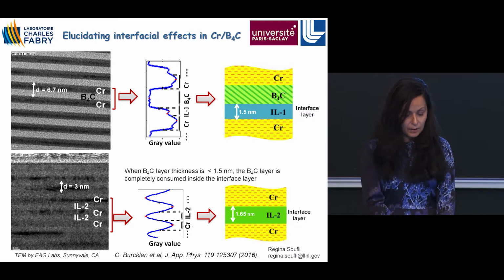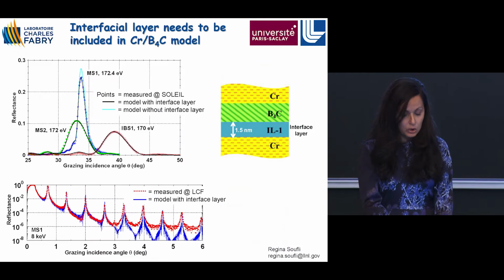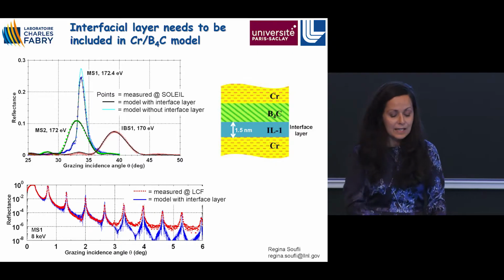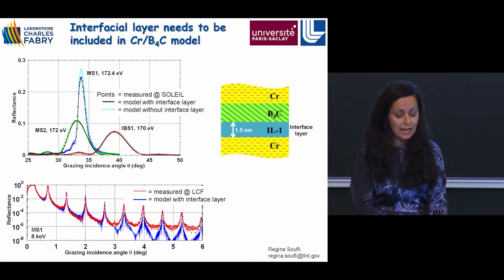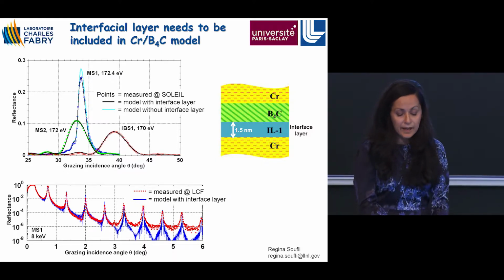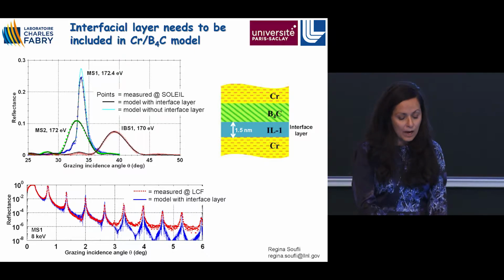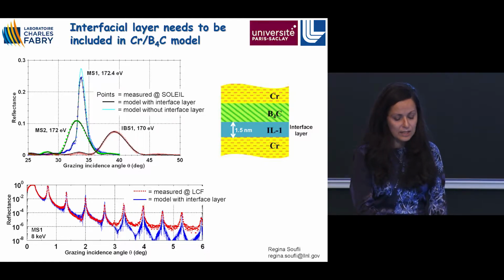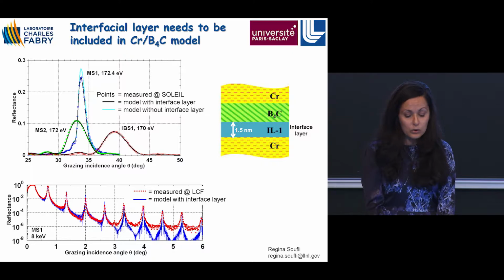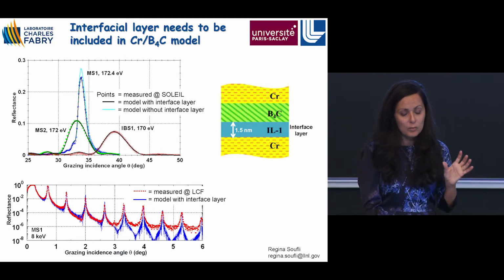So we pursued further measurements of this top sample, which is shown here in this curve, at different photon energies. And we determined that this interfacial layer that I was showing in the previous slide, it is essential that it be included in the model that we make for the multilayer. Otherwise, you cannot get an accurate representation of the reflectivity. And I'm showing here again the measurements of this sample. If you use the 3-layer model and you include the interdiffusion layer, you can have a beautiful model. And actually on all 3 samples, there is two other samples that I'm showing here that we measured at Soleil. If you only try to make a model with just the chromium and B4C layers, you will never be able to predict the reflectivity accurately.